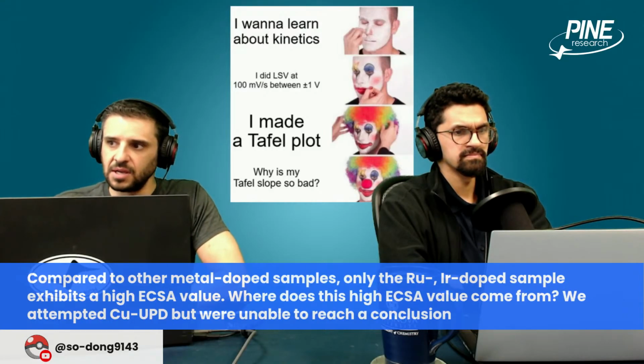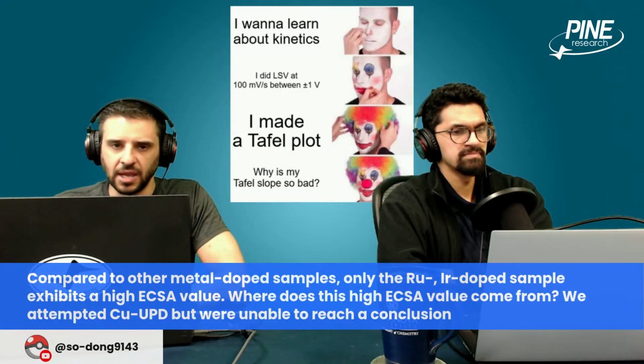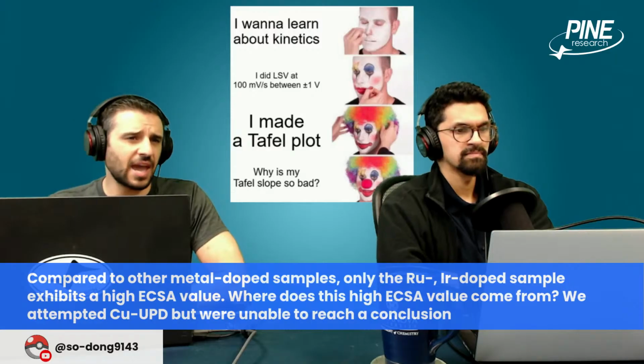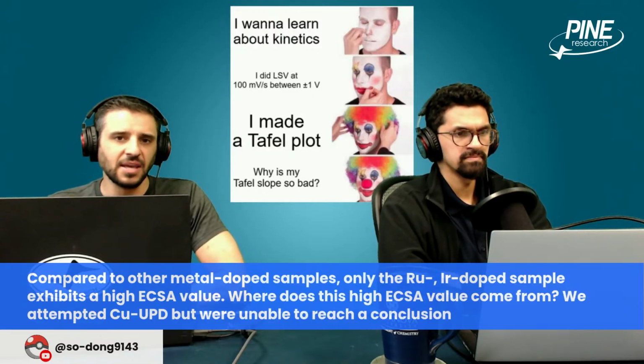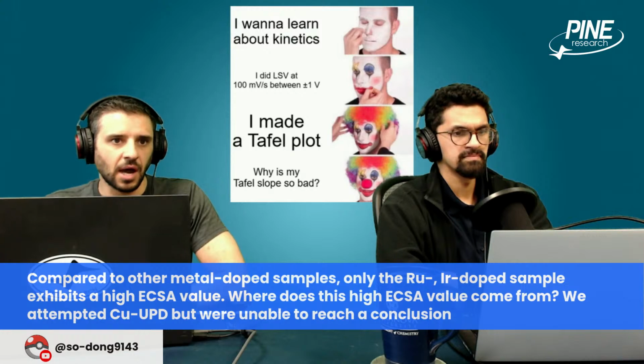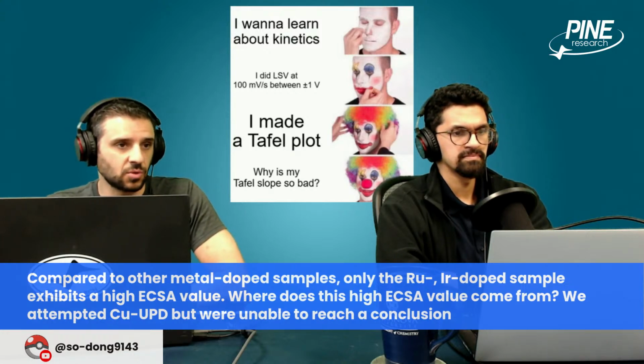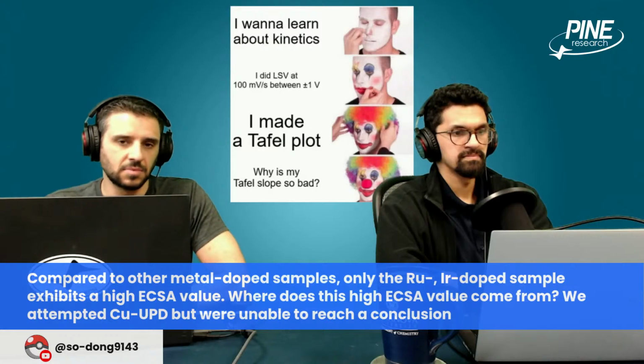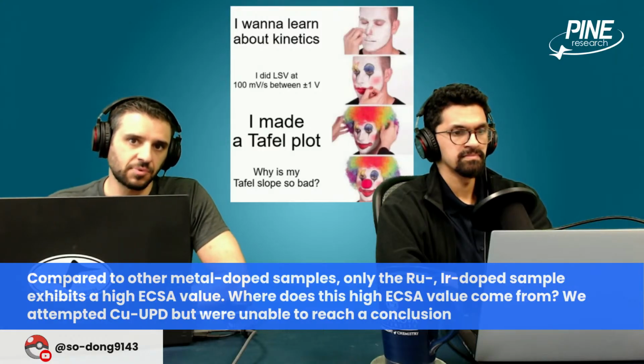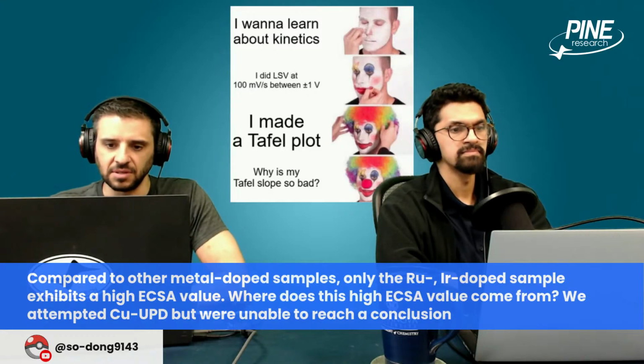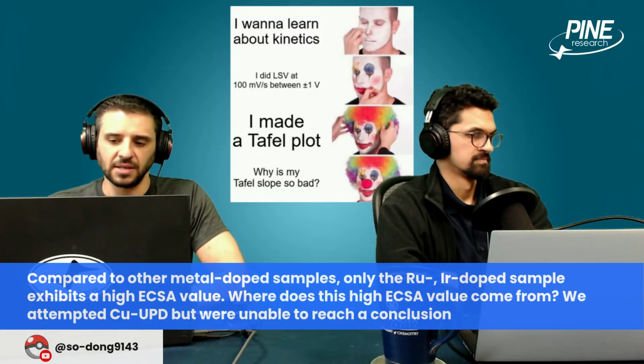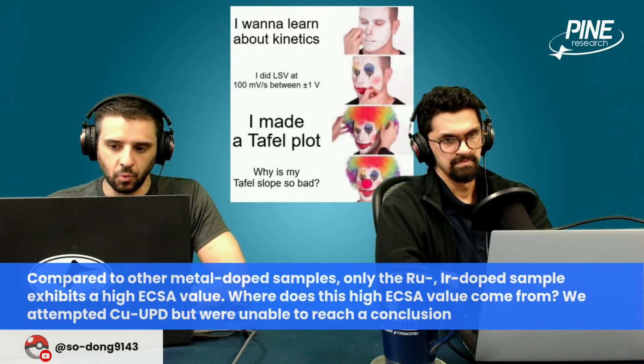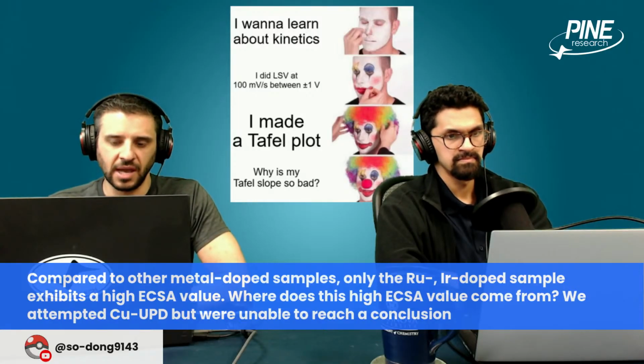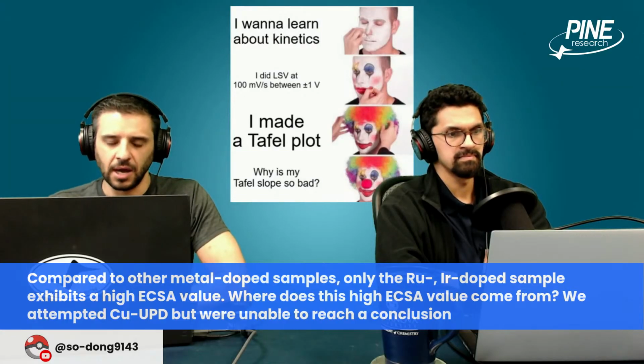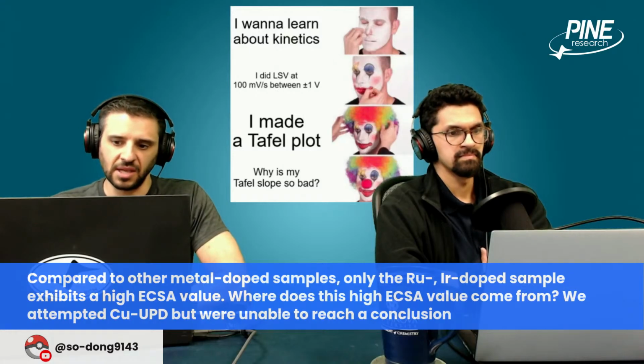The only way to interrogate some of that would be to do some kind of elemental analysis like EDX or XPS, to see, I did this dopant, do I have ruthenium on the surface, and do I have the same amount of dopant for each of these processes? It sounds like you're doing a lot of different materials, different metal dopants, and they don't all work the same. Not every element has the same binding energy and the same adhesion, so to speak, on whatever substrate you're using. So that could be the answer.